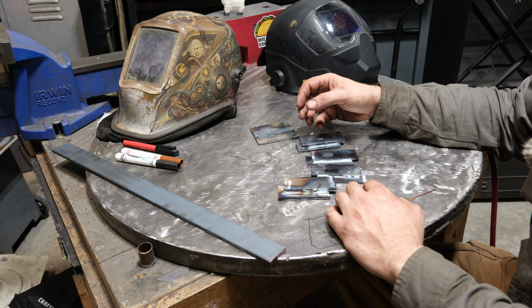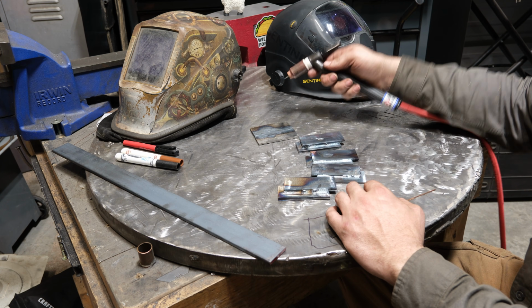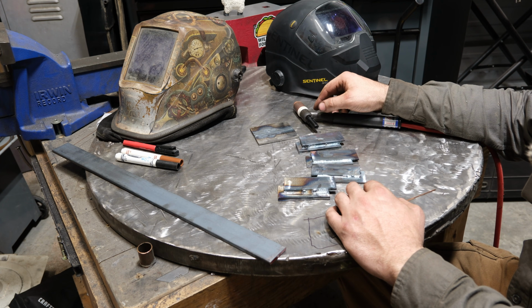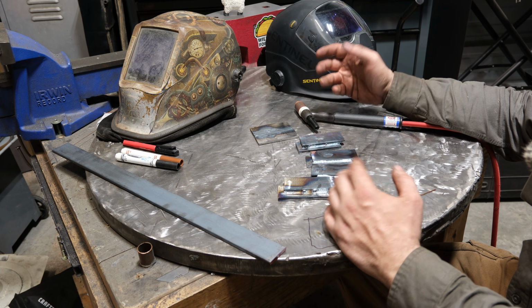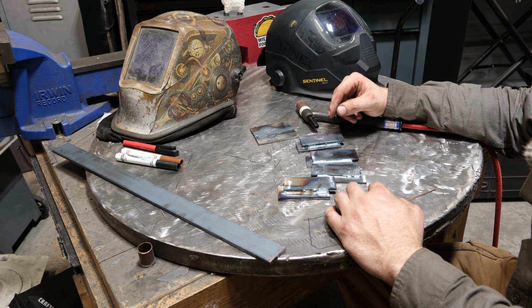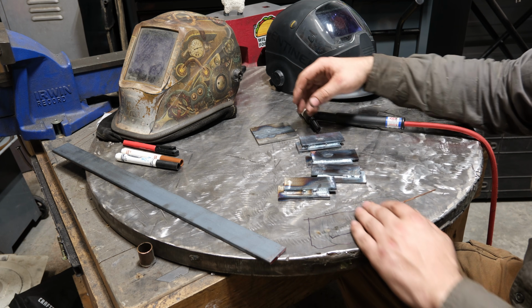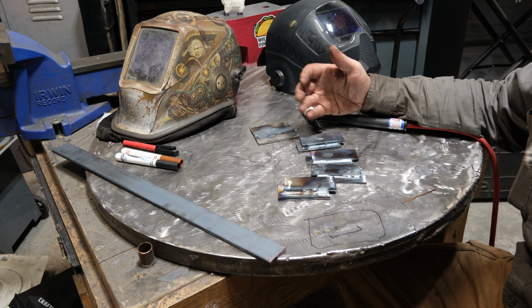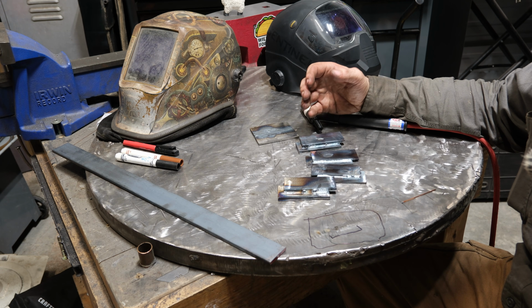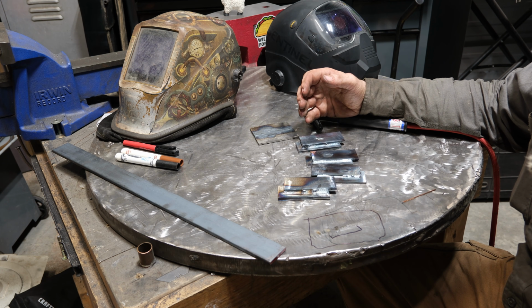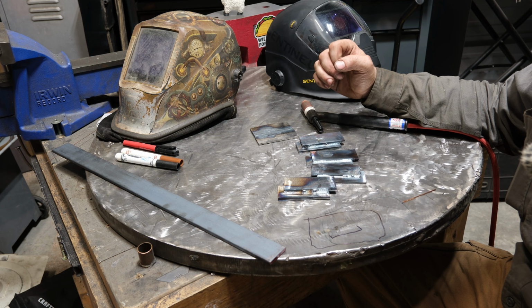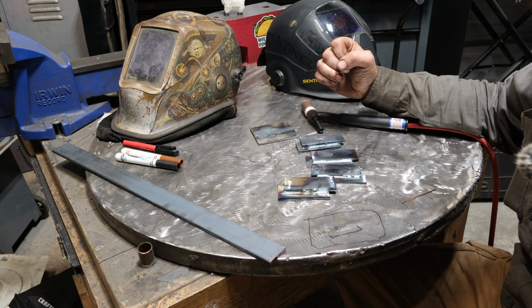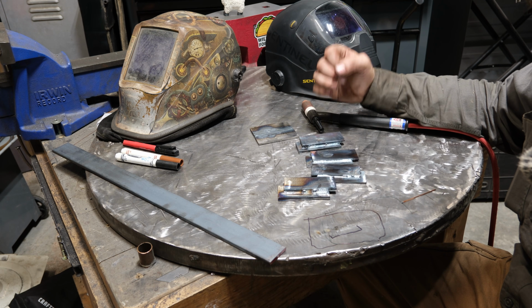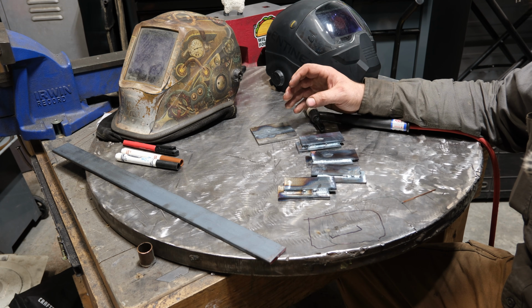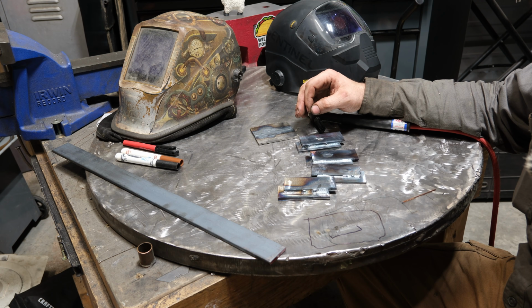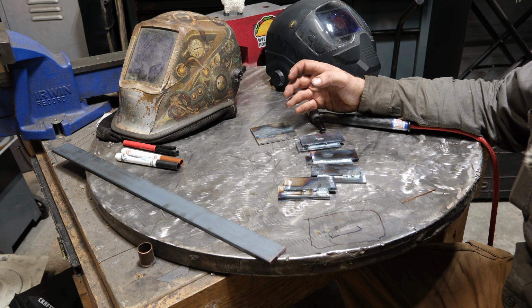So there's all sorts of ways you can do thick metal, but let's face it, the reason you're using TIG is to make high quality welds and likely on thinner material. And in that case, oftentimes all you need is 1 pass to make it good. And the key takeaways, as always with TIG welding, is you've got to maintain a consistent arc gap, you've got to be smooth, and you have to add filler material consistently. It's just 100% it comes down to consistency, and the more consistent you are and the smoother you are, the better your welds come out.